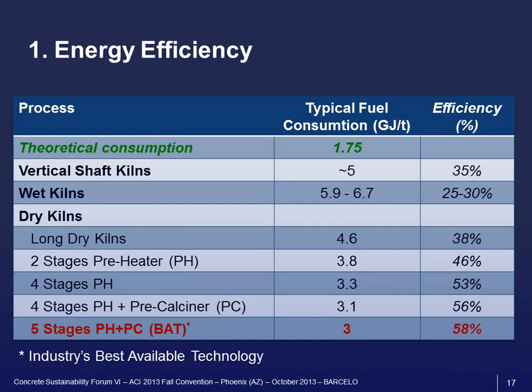And when you look at the theoretical energy consumption you need just for the chemical reaction that happens inside the kiln, you see that you need 1.75, so that means that your efficiency with this best available technology is 58%, which is quite good. In fact, it's better than the engine we have in the car.